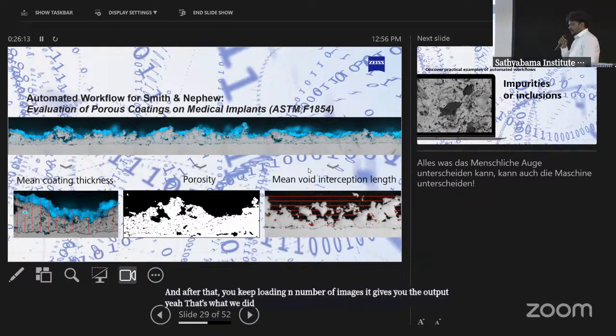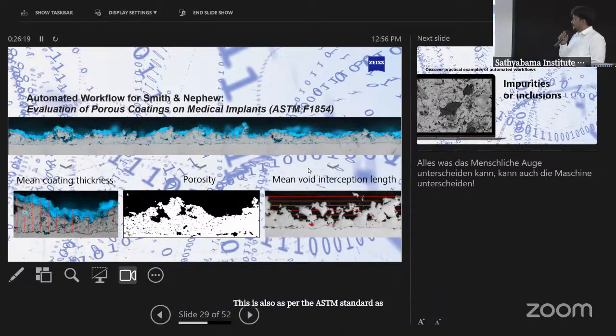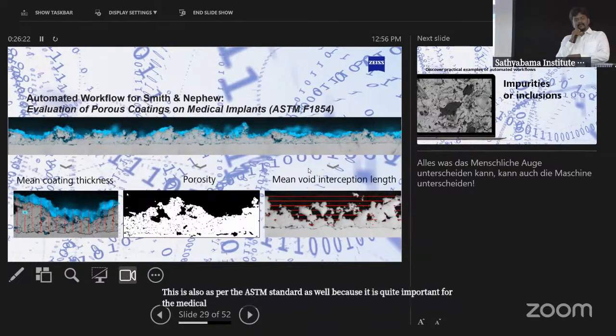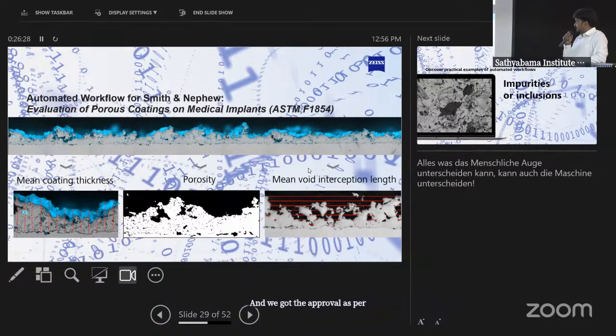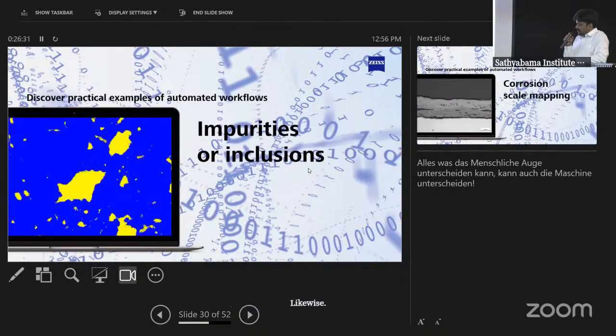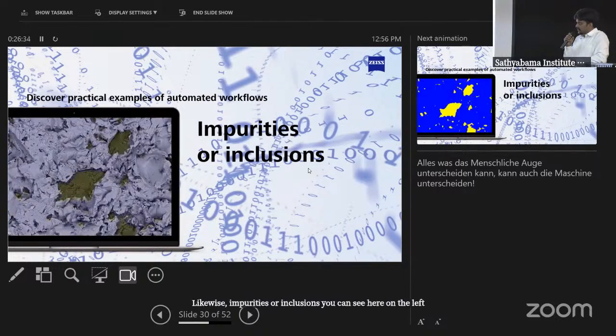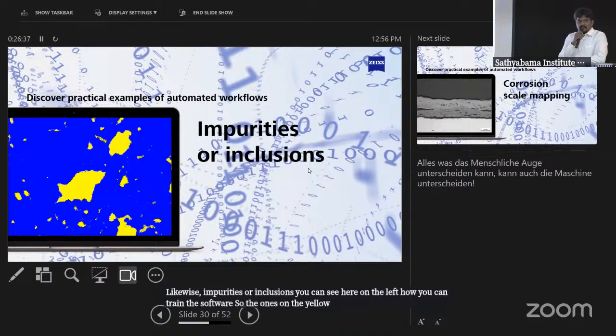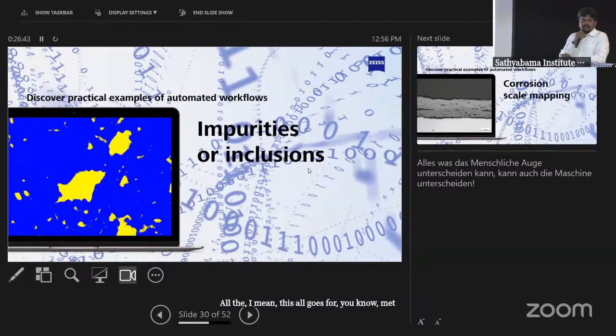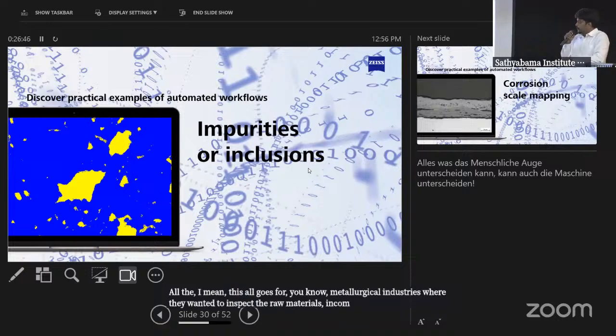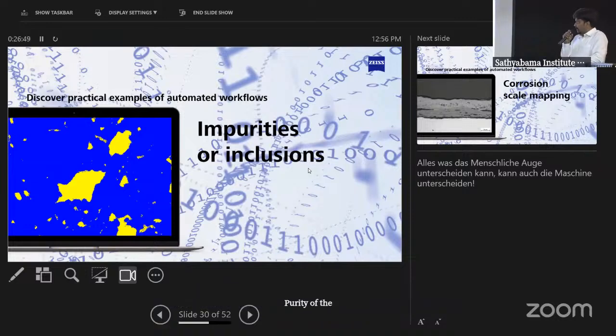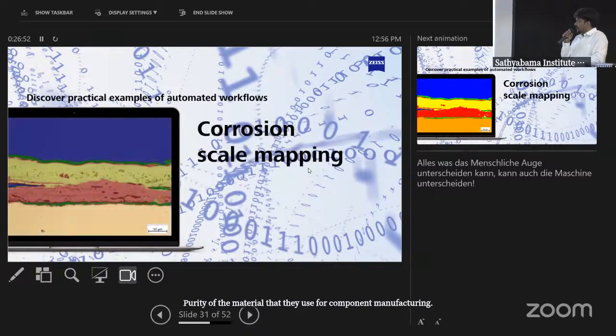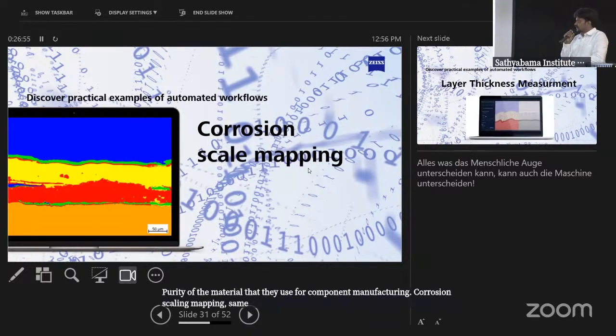And this is not just post-processing software. This is also as per the ASTM standard, because this is quite important for the medical implants. This we developed along with the medical implant manufacturing industry, and we got the approval as per the ASTM standards as well. Likewise, impurities or inclusions, you can see here on the left how you can train the software. So the ones in yellow are the inclusions, you do it for one of the images. This all goes for metallurgical industries where they want to inspect the incoming raw materials for purity of the material that they use for component manufacturing. Corrosion scale mapping, same thing. You train the software, it starts doing it on its own.